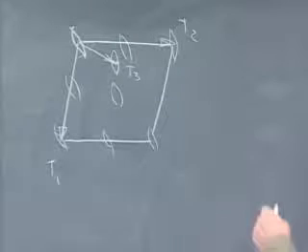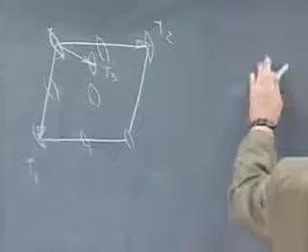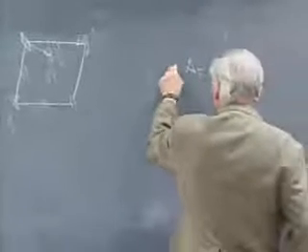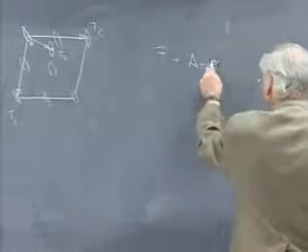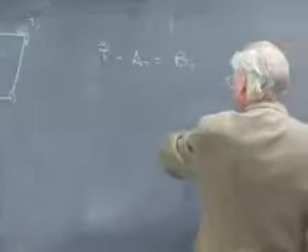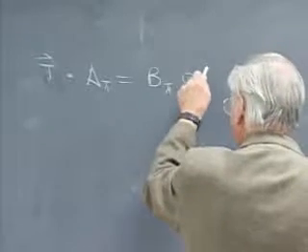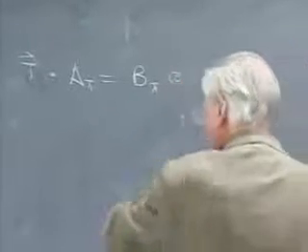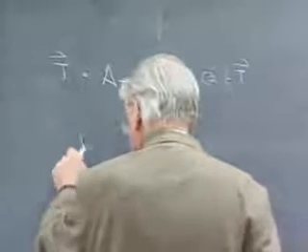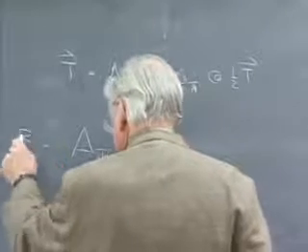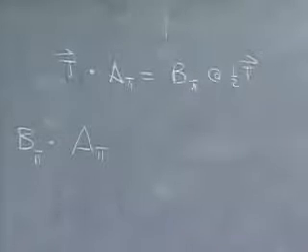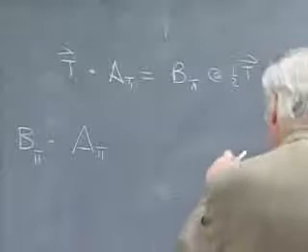And we can take one of the theorems that we've seen, namely that the operation A pi followed by translation is equal to a new rotation operation through pi located halfway along the translation, and turn this around and ask what happens when we combine 2 rotations through 180 degrees about different points. And let's just draw it out to see what happens.